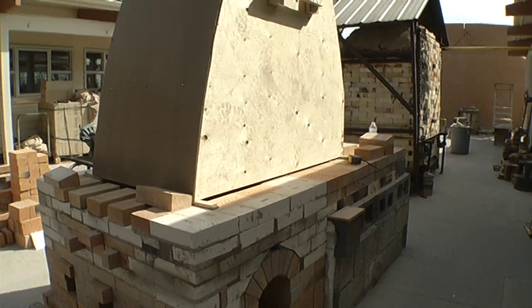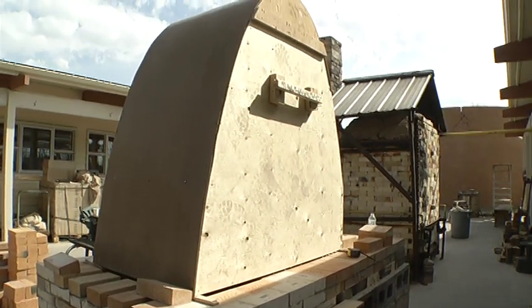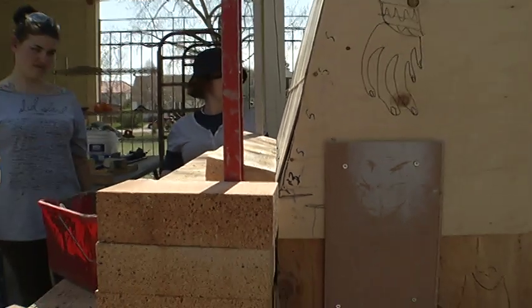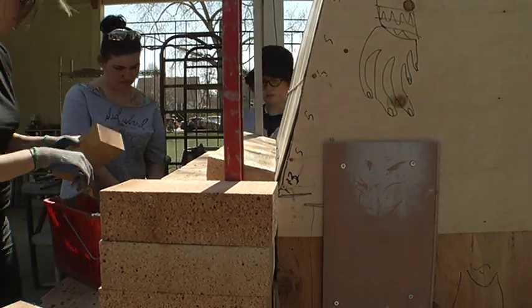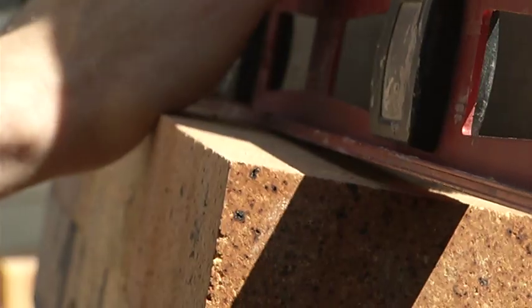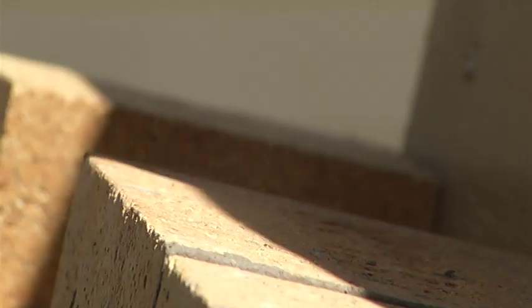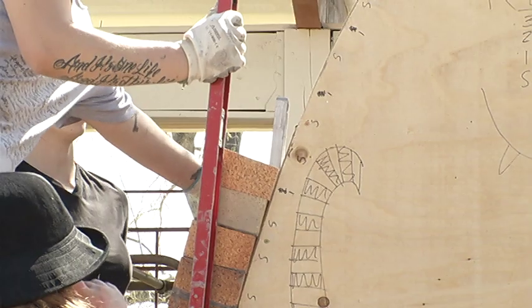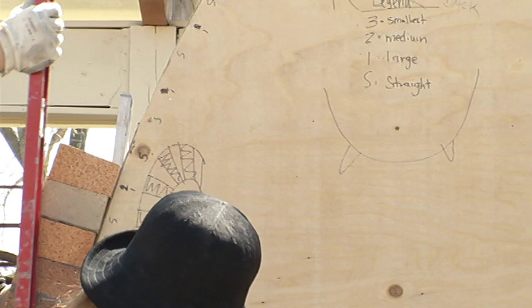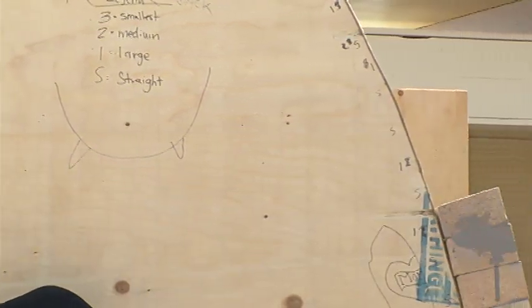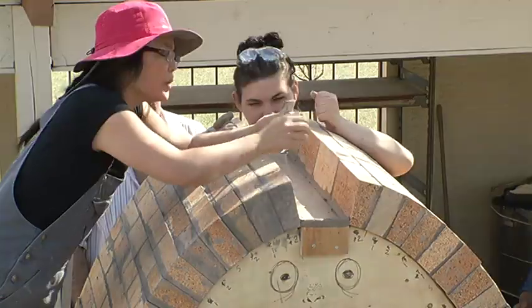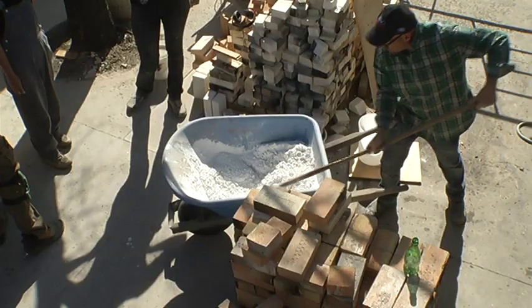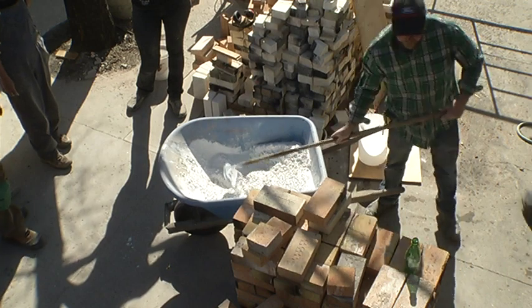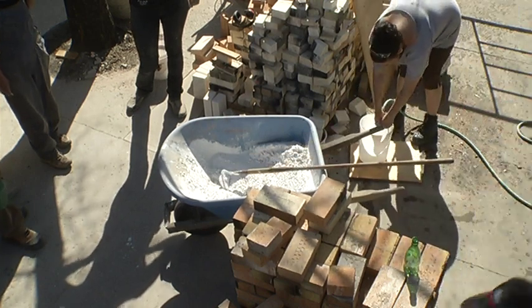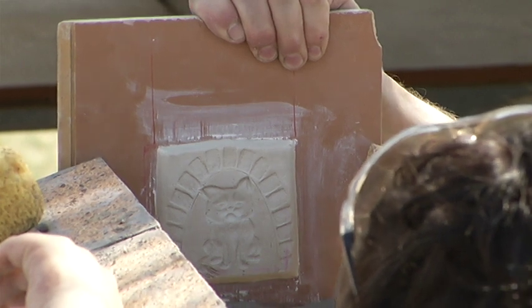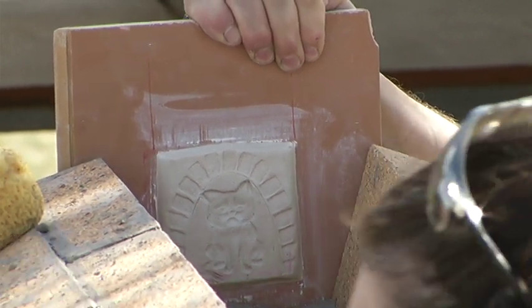We positioned the form on the kiln firebox base structure and started laying the hard brick for the first layer of the kiln. The arch construction required the most attention to maintain level and squaring edges. We built both sides of the arch at the same time to balance the weight load until we could cast the keystone in place. The keystone was made with high alumina fireproof mortar to withstand the tremendous temperatures of the kiln, and included a small cat motif in honor of our catenary arch.